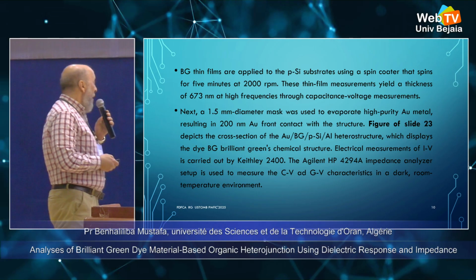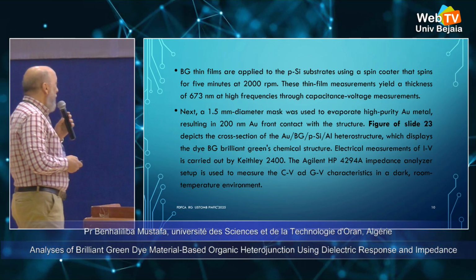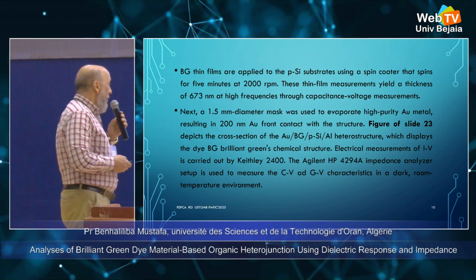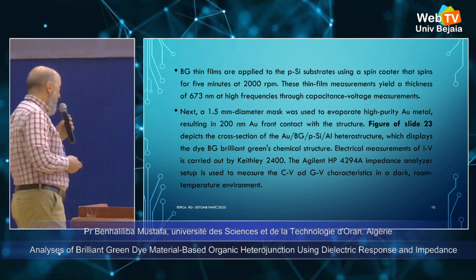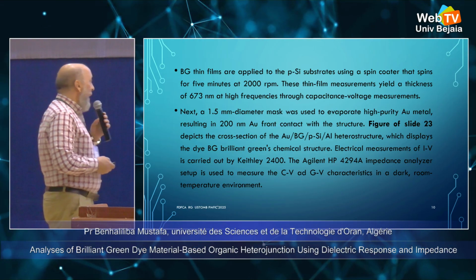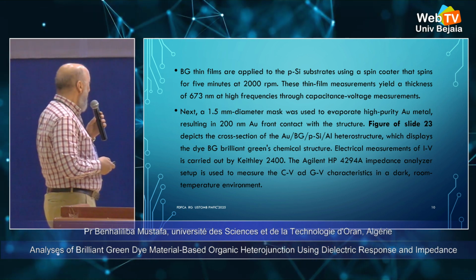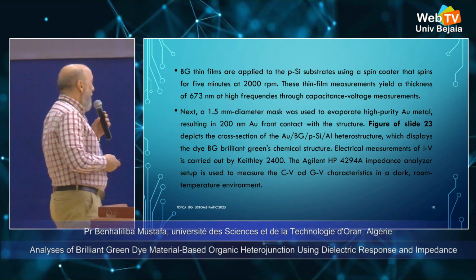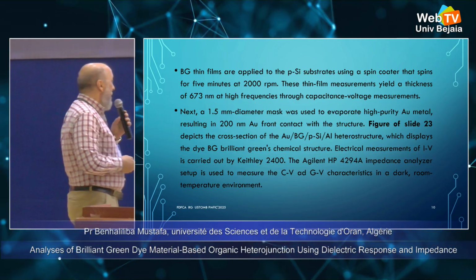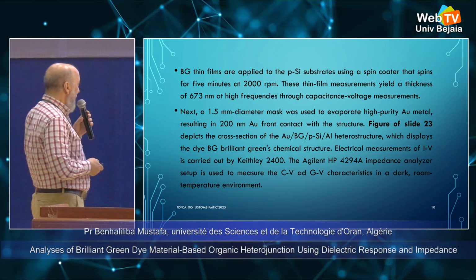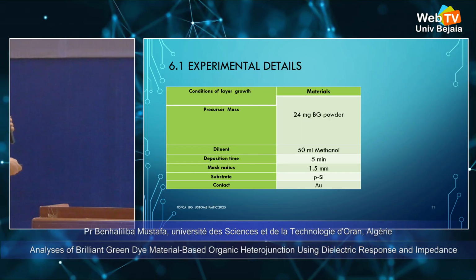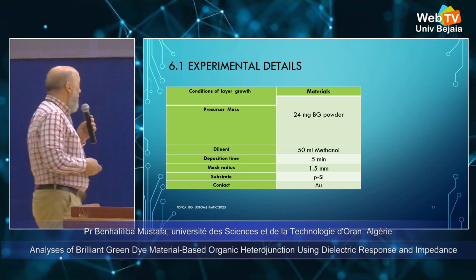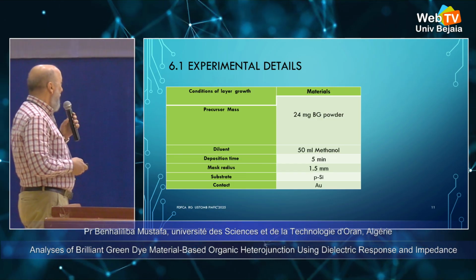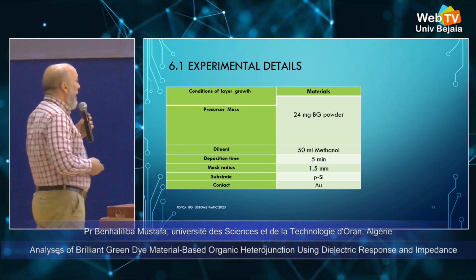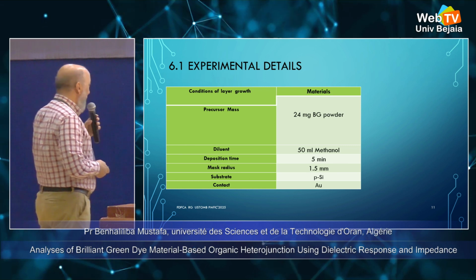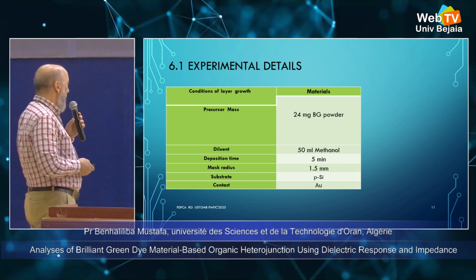Next, a 1.5 millimeter diameter mask was used to evaporate 200 nanometer gold front contact. The figure displayed on the slide depicts the cross section of the Au/BG/p-Si/Al heterostructure, which displays the dye BG brilliant green chemical structure. Later, we make the electrical measurement of current voltage carried by a Keithley 2400, and the Agilent HP 4294A impedance analyzer setup is used to measure the CV and GV characteristics in dark and at room temperature. Some experimental details: precursor mass 24 milligram BG powder, diluent 50 milliliter of methanol, deposition time 5 minutes, mask radius 1.5 millimeter, substrate P-silicon, and the contact gold.